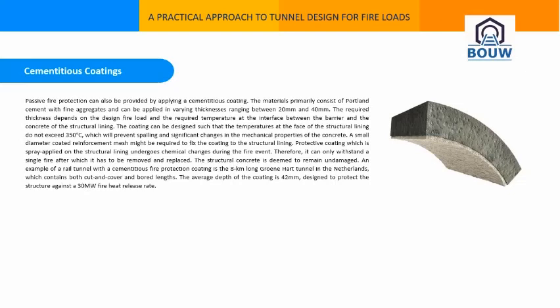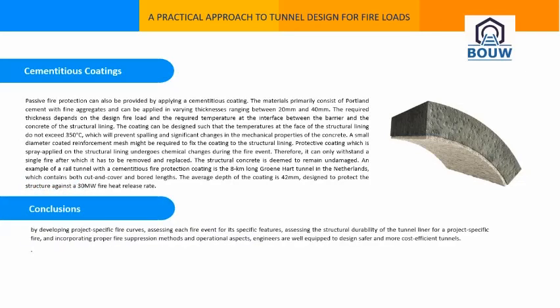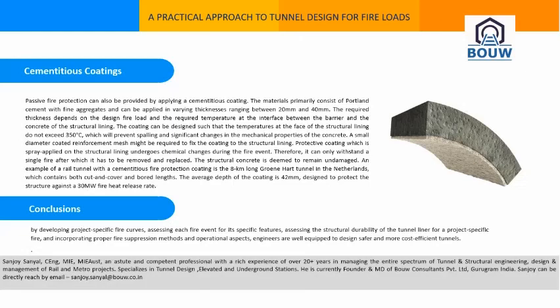An example of a rail tunnel with a cementitious fire protection coating is the 8 km long Groene Hart tunnel in the Netherlands, which contains both cut and cover and bored lengths. The average depth of the coating is 42 mm, designed to protect the structure against a 30 MW fire heat release rate.